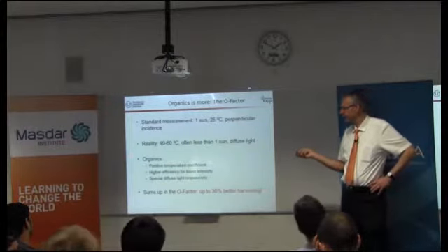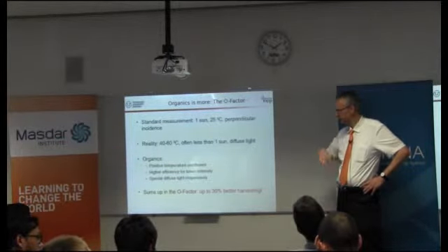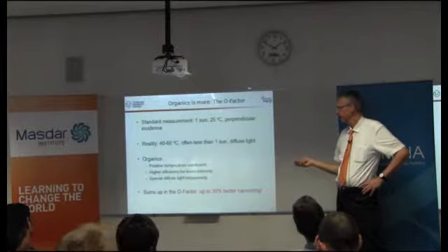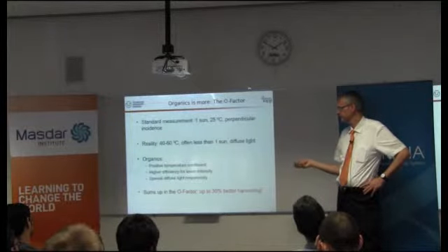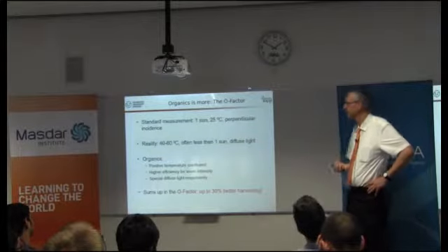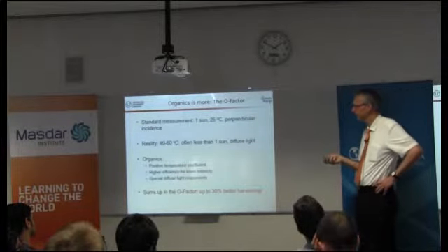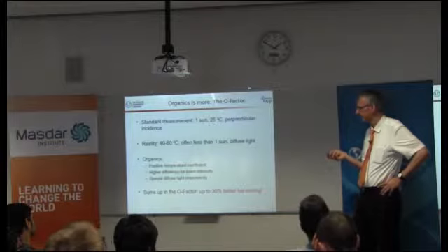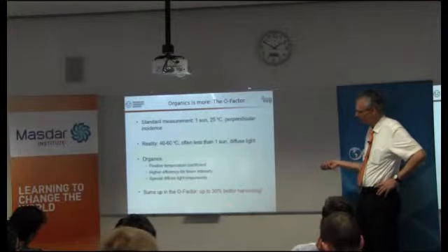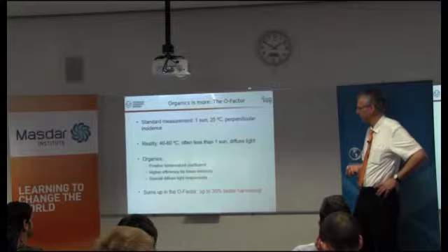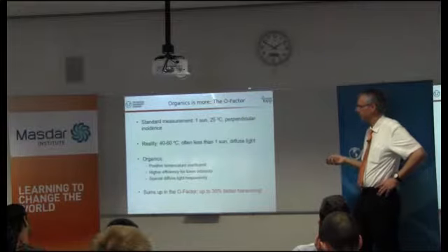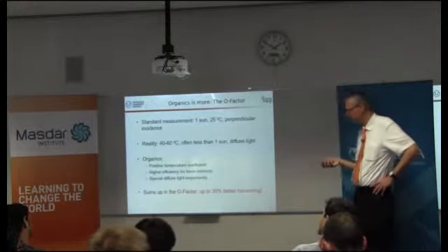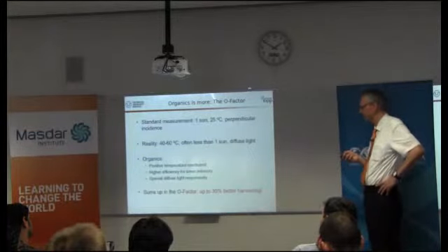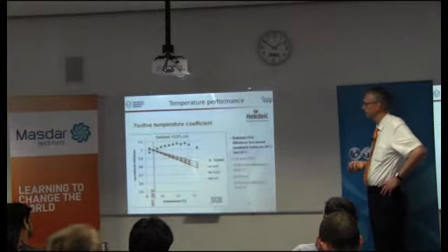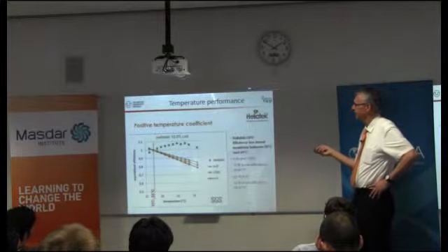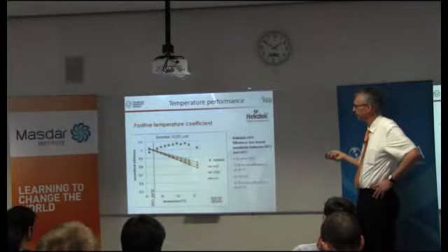And fortunately, organics has a positive temperature coefficient. It gets better when it's hot. It has a higher efficiency for lower intensity, and it actually has a super Lambertian behavior for the diffuse light responsivity. If you take it all together, we have measured in initial tests up to 30% better performance. So in other words, a 12% organic module compares pretty well to a 15% silicon module. To show you some data, this is a 10.3% cell produced by Heliatek.